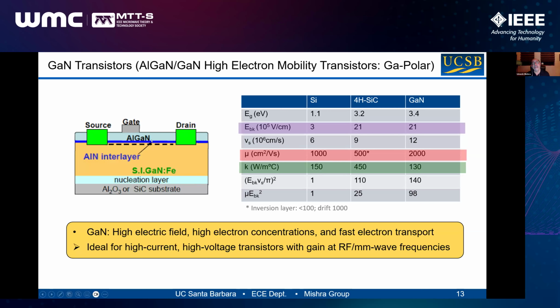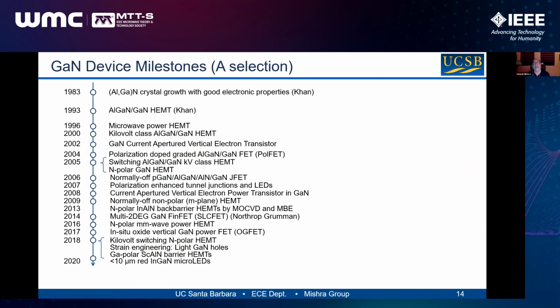And so you have like a silicon dioxide system. It looks like a MOSFET, but it's a MOSFET on steroids because the mobility of the electrons in this material is near 2000, and the mobility of electrons in silicon is 1000. So basically what ends up happening is gallium nitride has an unbelievable advantage over other material systems, mano a mano, device to device. I'm not talking about when you bring in beamformers, the integrated circuits associated with silicon that make silicon so attractive. But as a device to device comparison, there's no contest.